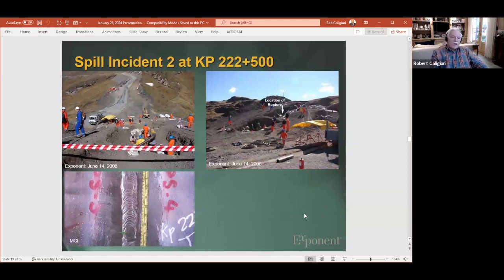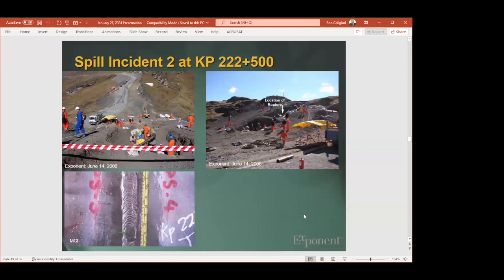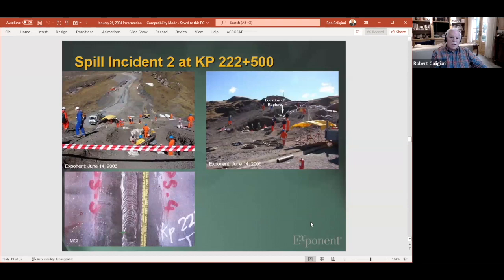These are the two that occurred in the crossing of the Andes. You can see the topology and the environment changes substantially as you climb up these mountains. And it occurred again kind of close to the peaks of the Andes, and you can see a picture of where it leaked. And here's our friend again down below, cracking a weld.